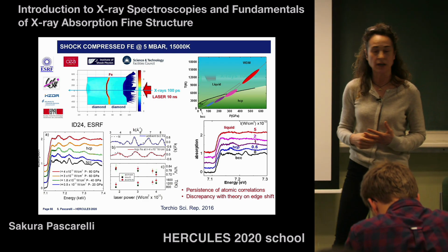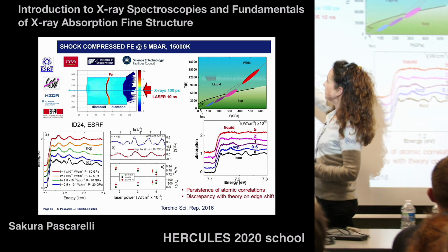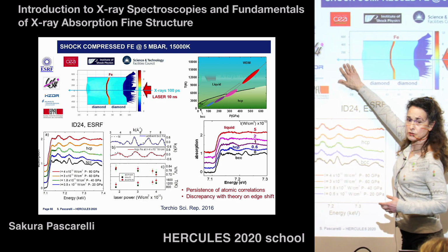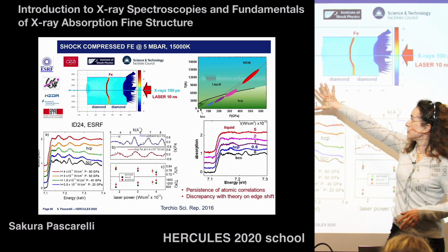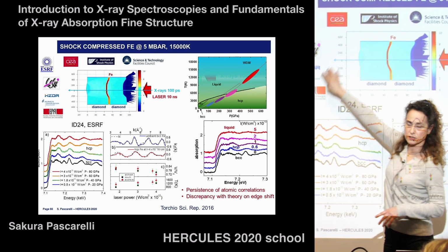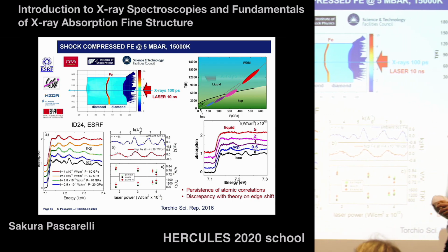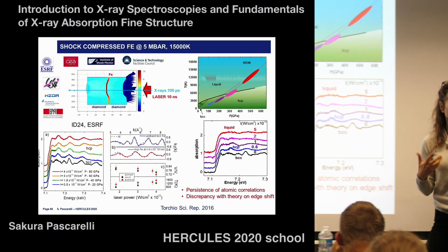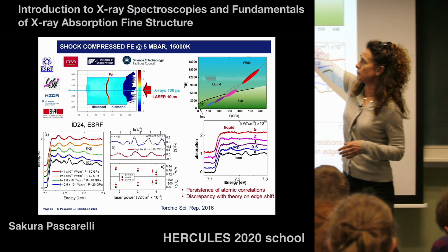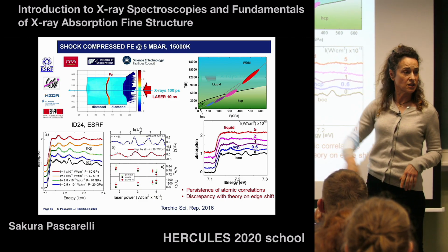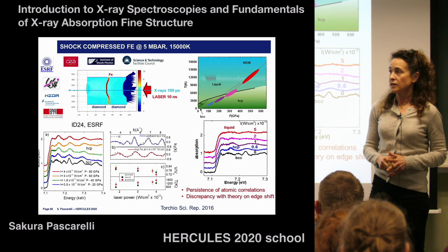We can add them. So how do we measure the pressure here? We can measure the pressure using an interferometer in the back, which measures the speed of the shock wave from the back. It's called VISAR. And we can measure the temperature using very fast pyrometry. So all this is really complicated. You see, we were collaborating with many, many different institutes. These are big collaborations.